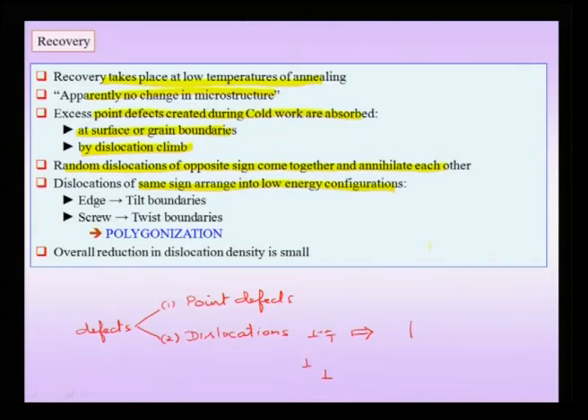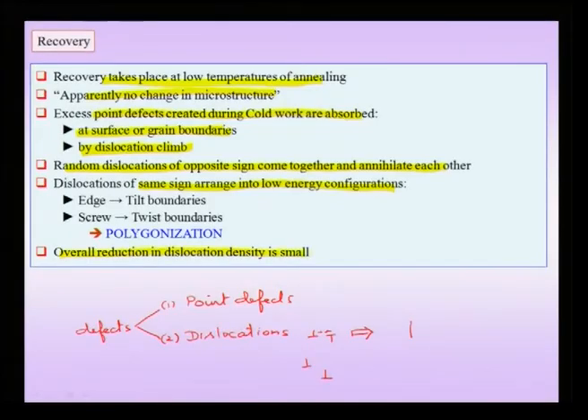So, the important point to note is that though there is a small reduction in dislocation density and there are some low energy configurations which are arising during this recovery, the overall reduction in dislocation density is small. This is an important point to note, and when these dislocations of same sign come together, for instance the